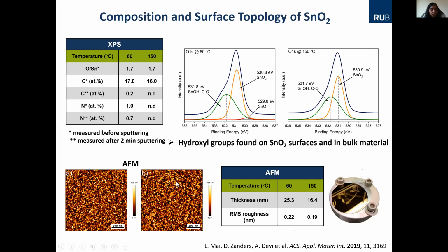Again, we looked at the AFM, and you see the roughness is pretty low. In the previous slide, the CVD, I showed you that the roughness is around 10 nanometers, but here you have less than 0.2 nanometers, which is a good sign that the film is very smooth, dense, and we get very conformal coverage.